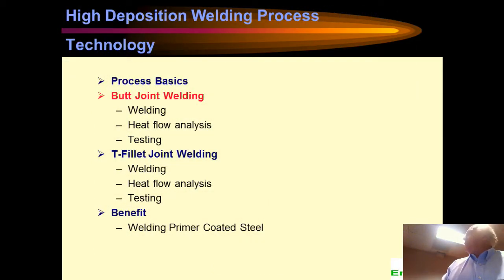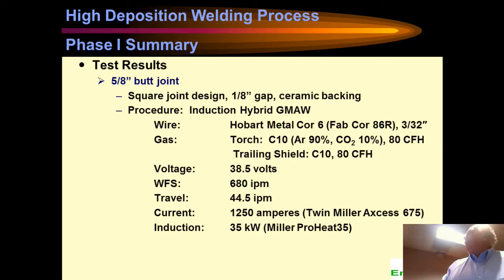So let's look at the butt joint welding we've done. I got a couple of examples. We were using Hobart Metal Core 6, which has been renamed. It's now FabCore 86R. 3/32 inch wire that we're driving in there at about 680 inches a minute for the 5/8 inch material. 1250 amps. We're using 2 Miller Axcess power supplies. And then we have the 35 kilowatt induction power system out in front of it.